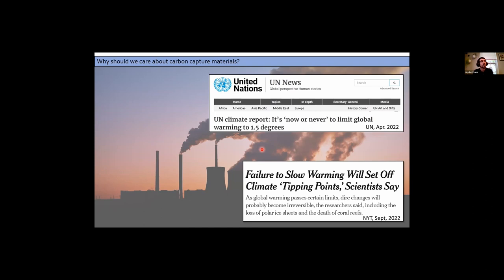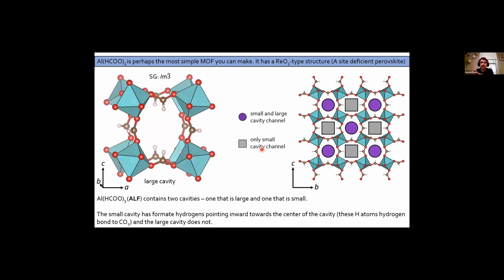Both of these are complicated in their own rights, and you need to find the right material for everything. And so the material that we've been looking at, and I'll skip some of the background and how we even got here, but know that the material we've been working on for like 2 years, basically at this point, is aluminum formate. It is probably the most simple MOF you can even devise. This is a very simple linker. It's dead simple, but the material is so remarkable. It has an ReO3 type structure, so it's like an A-site deficient perovskite. So you have these empty sites in the center here.